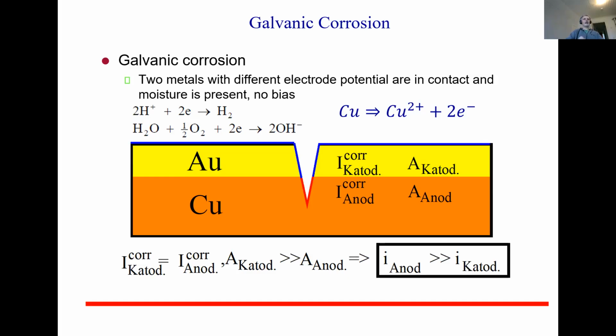So what it means is that because in a cathodic reaction we consume as many electrons as are formed in the corrosion dissolution reaction, the currents must be equal. If this surface area is much smaller than this one, then the current density, which is also directly proportional to corrosion rate, is very high here. So locally, this less noble metal starts to corrode fast underneath the more noble metal.